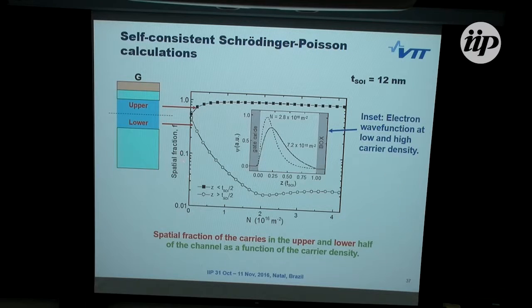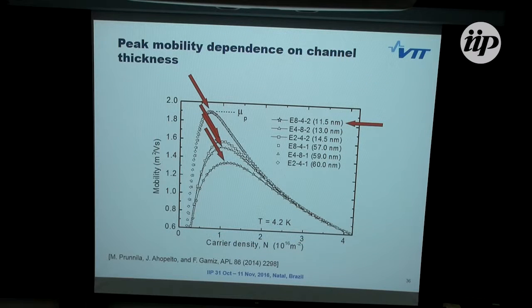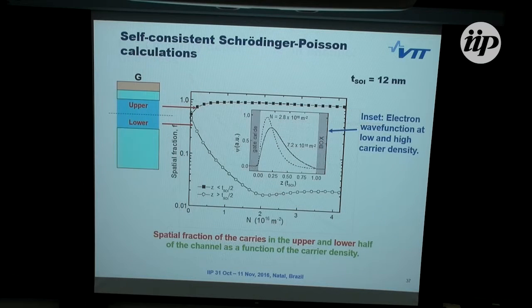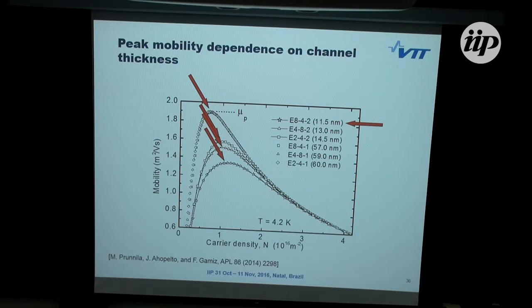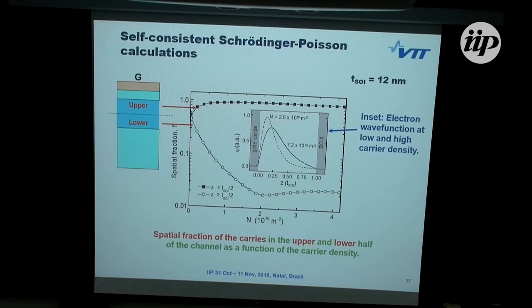This is the spatial fraction of carriers in the channel, in the upper and lower part. This is the upper half towards the gate, and this is the lower part towards the buried oxide. At low gate voltage, which means low carrier concentration, the tail actually sees the backside of the channel. And for some reason, this interface is not as good as this one, and this actually affects the peak mobility in this part at lower carrier density. If the carrier density is increased, the majority of the carriers are at the front interface, and they don't feel the backside anymore. So these all approach the same value. This is rather understandable.